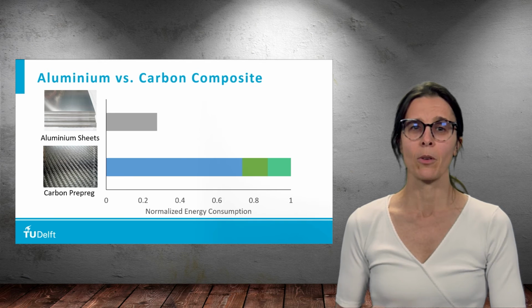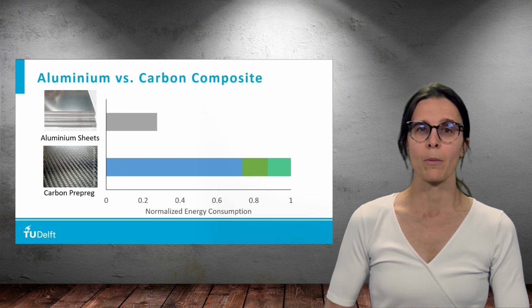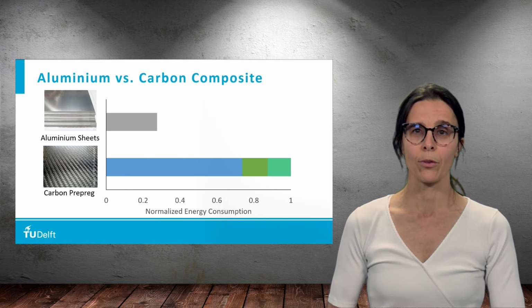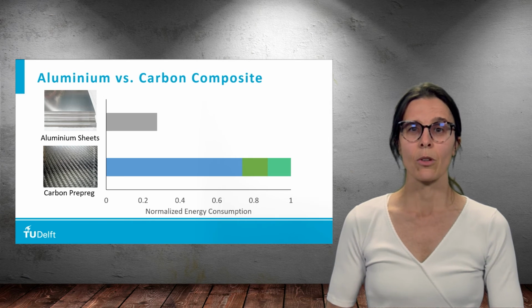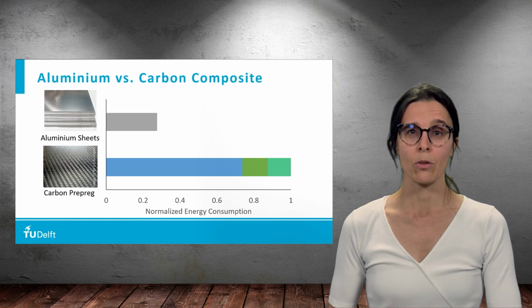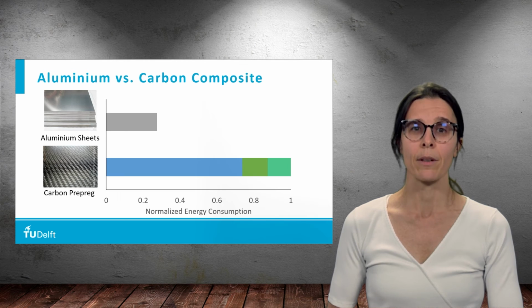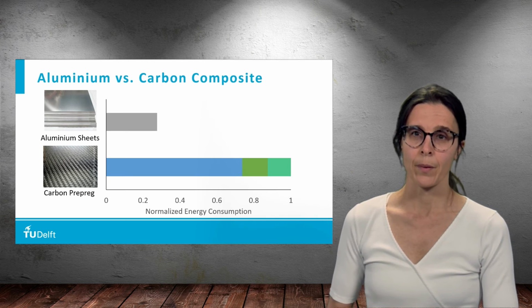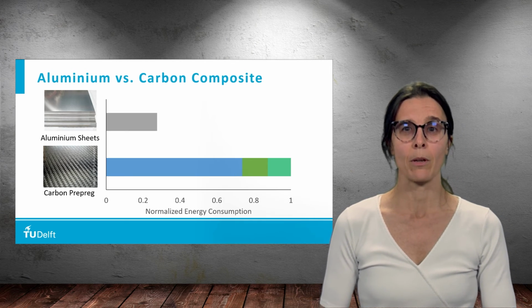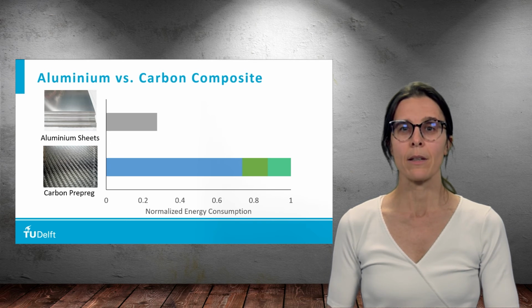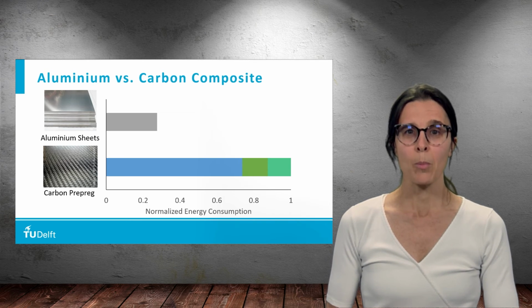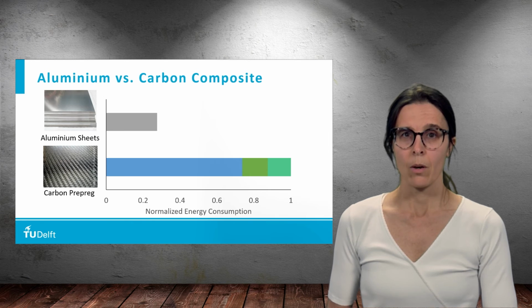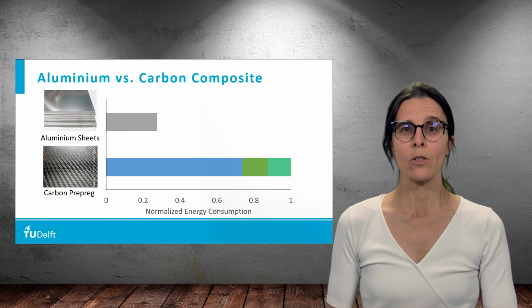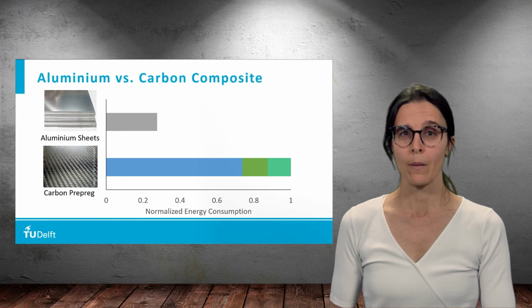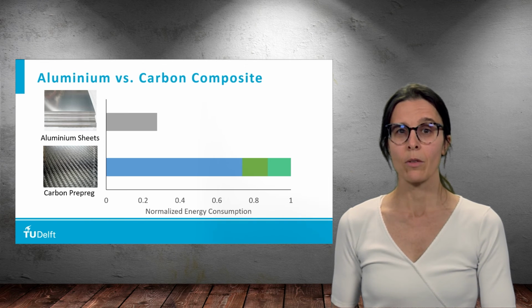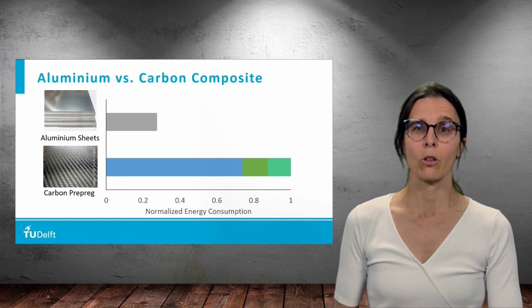So as it seems from this comparison, the material shift from aluminum alloys to carbon composites to build aircraft structures results in lower emissions during operations, but makes manufacturing significantly more energy intensive. The good news is that the carbon composite manufacturing industry is relatively young, and therefore it has ample room for optimization, with estimated potential energy savings that amount to 85%, considering both state-of-the-art best practices and ongoing research.